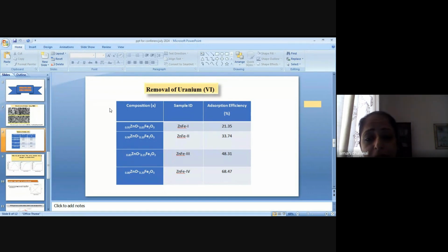So the adsorption experiments were performed for the removal of uranium. In the first composition, zinc oxide is 0.95, and on the other hand, the other component is 0.05. Similarly, four batch experiments have been performed. In the first one, the adsorption efficiency was reported as 21.35%, and it goes on increasing with the composition, to 48.31%, and at the last, 68.47% removal of uranium has been achieved using these prepared nanocomposites.